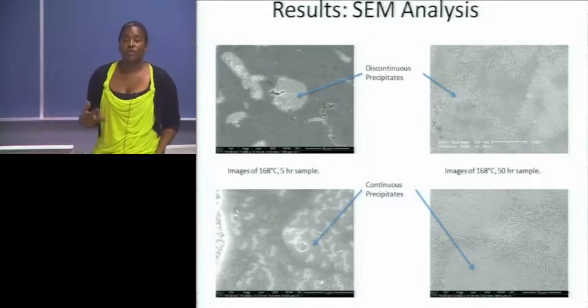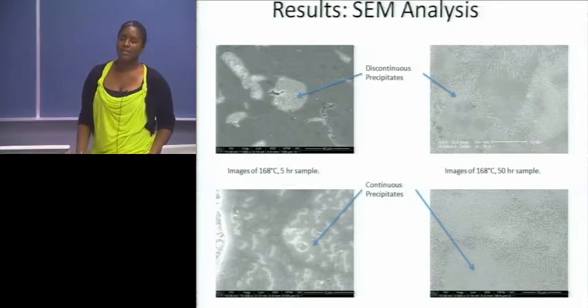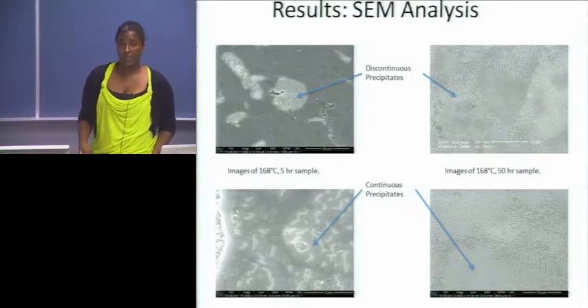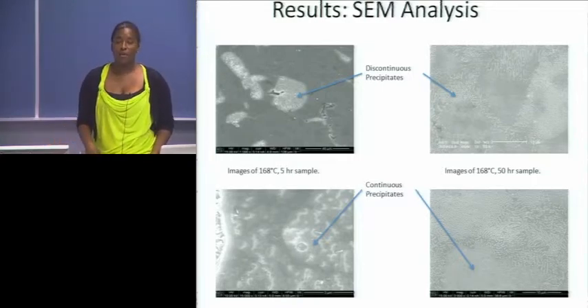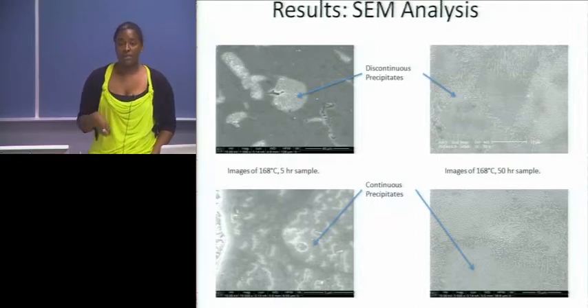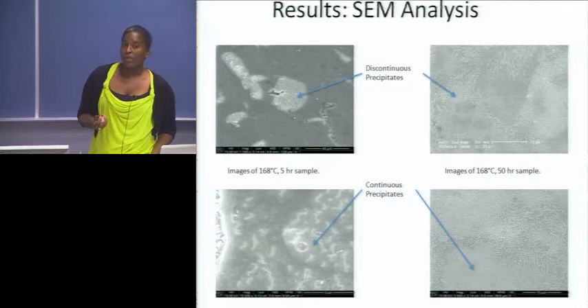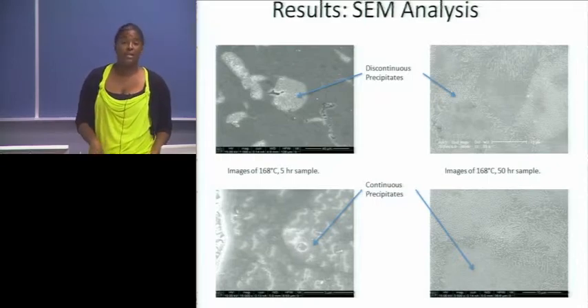Then after my project was done, I concluded, and I did find that both discontinuous and continuous precipitates did increase with aging time. Also, I did microstructure analysis of the tensile tested specimen and found that there was no twinning, so plastic deformation probably occurred due to dislocation slip.